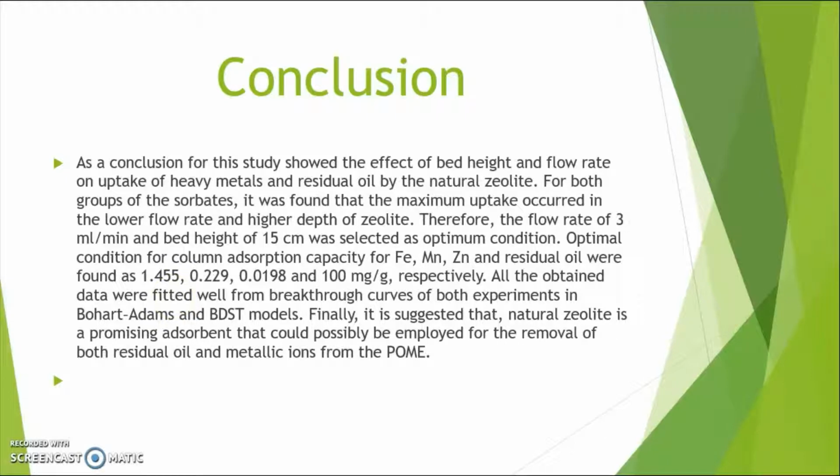So, the last part is the conclusion. As a conclusion, the study shows that for the effect of bed height and flow rate on uptake of heavy metal and residual oil by the natural zeolite for both groups of sorbents, it was found that the maximum uptake occurs at the lower flow rate and higher depth of zeolite. Therefore, the flow rate of 3 milliliter per minute and bed height of 15 cm was selected as optimum condition.